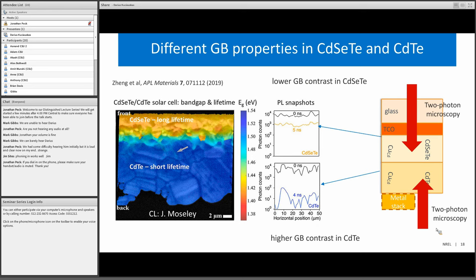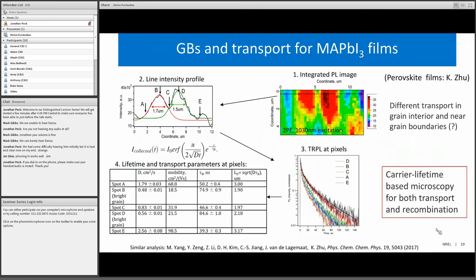Now, if we look at perovskites, then another aspect becomes interesting. If we measure lifetimes, the lifetimes do not always mean recombination. When we're doing measurements with a focused laser beam, which is less than 1 micron in size, carrier transport, carrier drift and diffusion can also be measured using the same approach. And here, illustration one shows two bright red grains in the middle of the image. Then image two shows the linear intensity profile. And then image three shows TRPL decays at pixels A, B, C, D, and E.